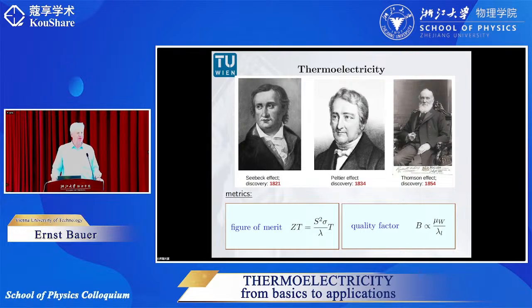Unfortunately, not only the Seebeck effect is of importance in this thermoelectric energy conversion, rather we have to consider beside the Seebeck effect also the electrical conductivity of the very same piece of material, as well as the thermal conductivity. When putting these parameters together, we end up with the so-called figure of merit. So the figure of merit, when multiplied with absolute temperature, reveals a unitless quantity, and this is at its optimum if this constant becomes larger than 1.